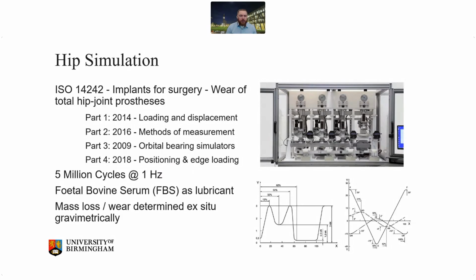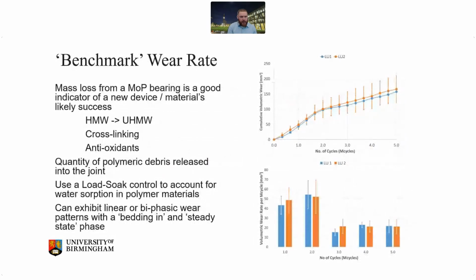wear rates essentially. So what we've ended up with is this measure of a benchmark wear rate as a successful standard, and that's driven a lot of the development around metal on polymer hips, mostly from a materials perspective. So from the switch from high molecular weight to ultra high molecular weight polyethylene, the addition of cross-linking in order to prevent delamination, particularly in knees, and also antioxidant polymers.